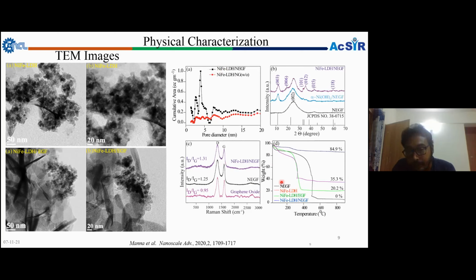So here you can see, without any metal, the support nitrogen doped entangled graphene, when we are heat treating in presence of oxygen, the residual metal presence after 400 is 0%. But in case of nickel iron layer double hydroxide without any carbon substrate, when you are heat treating, there is a change in the weight, because of the water molecules present in the intercalation structure. Already shown, the nickel iron layer double hydroxide has an intercalation structure. So in between two layers there is a water molecule, which may be connected through hydrogen bonds, and that is removed after 200 degrees centigrade, and that change is observed. So that's why there is a 16% weight loss, because of the intercalated water molecules.